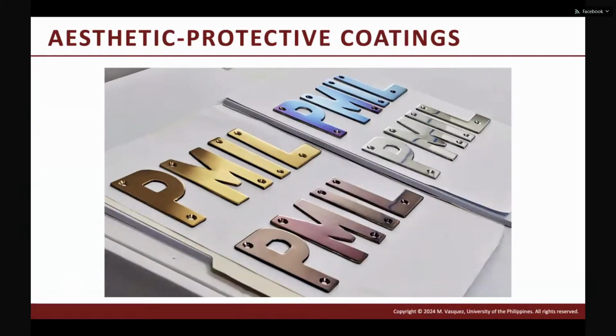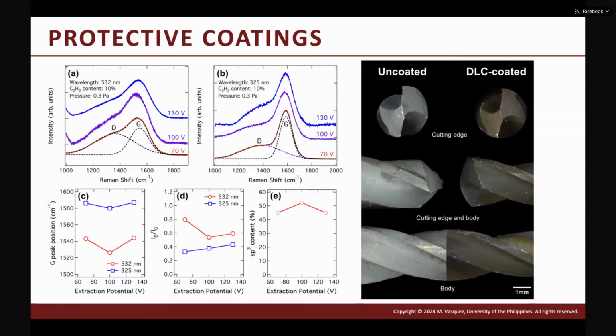So these are some of the coating colors that we have produced. So aside from gold, we tried rose gold, and on the further letters, I think we don't have a name for this, but it has a bluish purple hue. And that means that by tuning the different operating parameters of our deposition process, we can create different colors. We've done also diamond-like carbon coatings. So this is an example of a DLC coated drill bit. And we successfully deposited DLC and improved its hardness. We tested its hardness in terms of the number of holes that it can produce. And we were able to more than double the number of holes when the tool is coated with DLC.